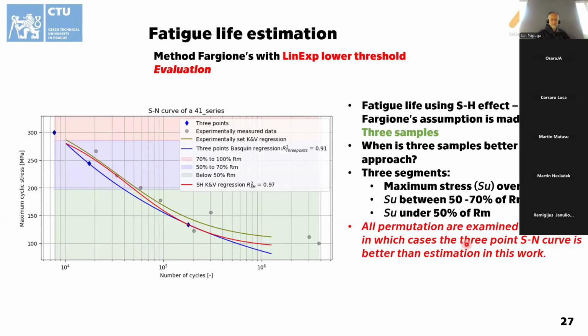To find out if it makes any sense to use this approach, I tried to compare this methodology to setting up the relation between the stabilized temperature in phase 2 with the amplitude of load, finding out the lower threshold, or in this case, the fatigue limit, and using the Fargione's assumption to make the SN curve, or to use only 3 samples for the SN curve. As you've probably seen in the past, some research papers tend to make conclusions out of 3 samples just to make the SN curve. So I'm just asking if it's better to use this methodology or 3 samples for conventional testing for single level amplitude till failure. So what we did was to set up 3 segments, basically.